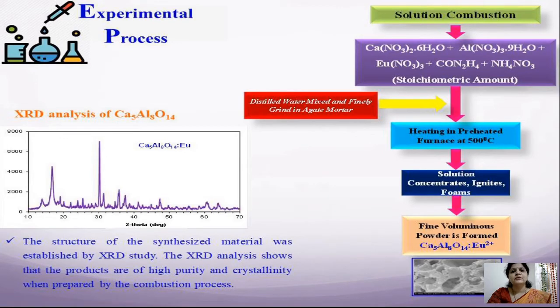Experimental process: the material was synthesized by low temperature solution combustion method. In this method, stoichiometric amounts of calcium nitrate, aluminium nitrate and europium nitrate were taken in a borosilicate beaker. Urea was added as a fuel and ammonium nitrate was added as an oxidizer. To this mixture, double distilled water was added dropwise to obtain a clear solution, which was then transferred to a preheated muffle furnace at 500 degrees Celsius. The mixture boiled, foamed and ignited to a voluminous foamy material. The foamy product was crushed into fine powder and used for further characterization.